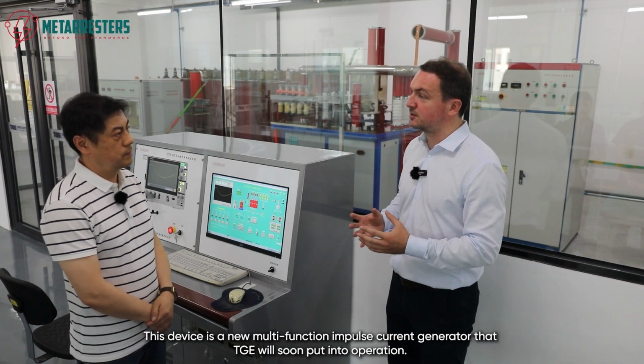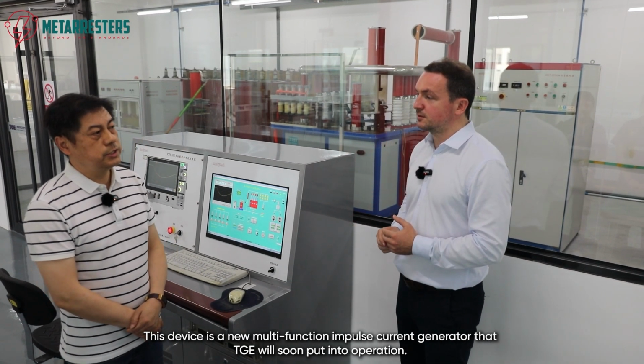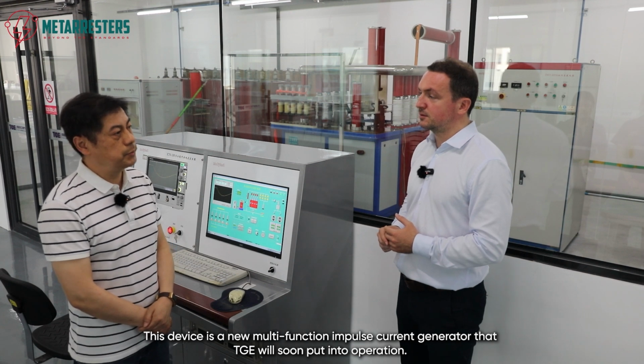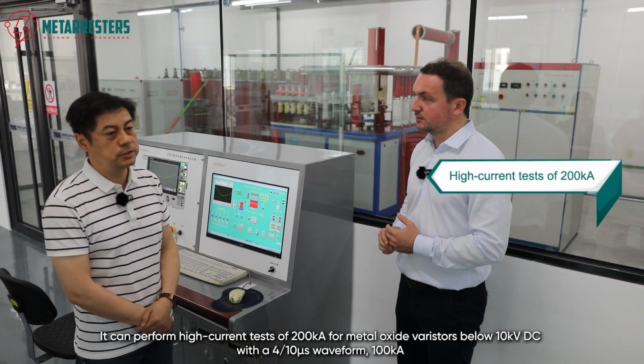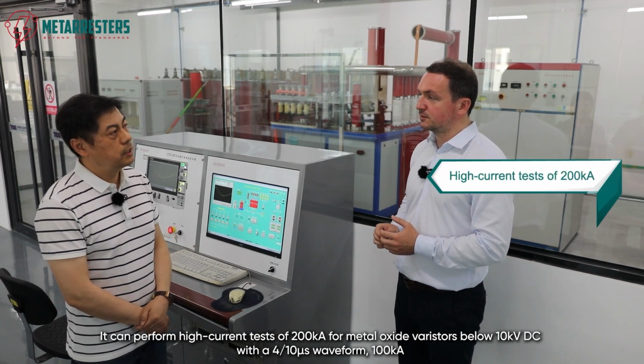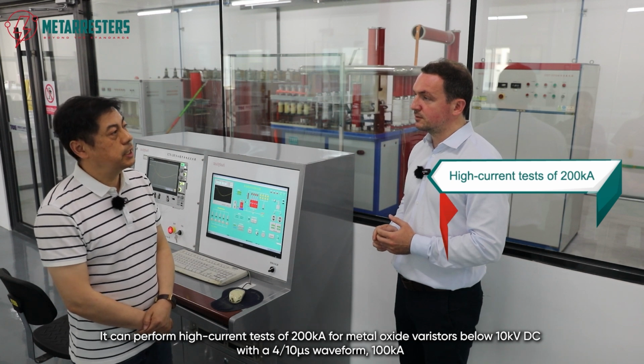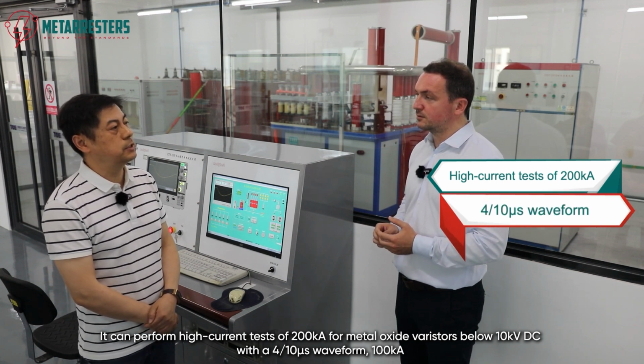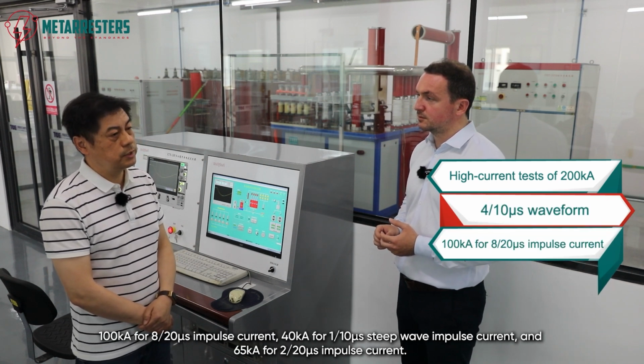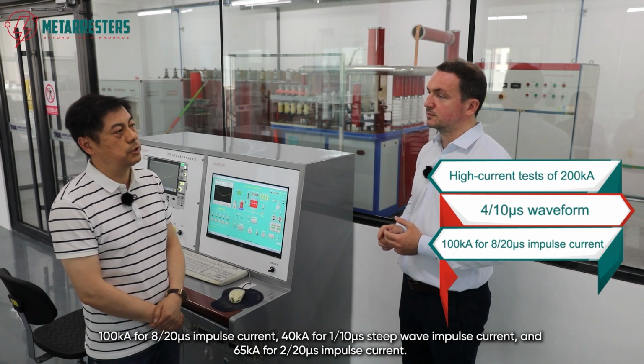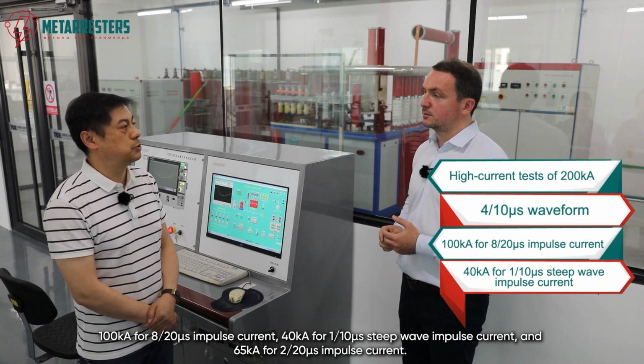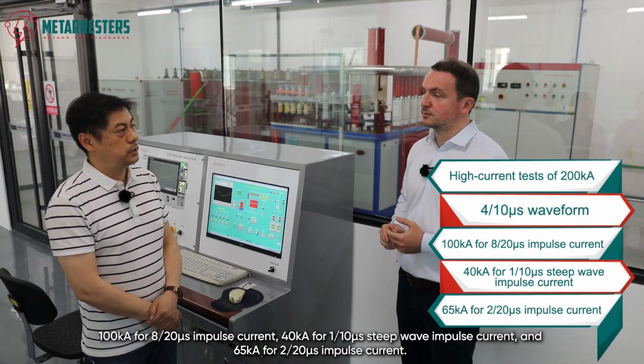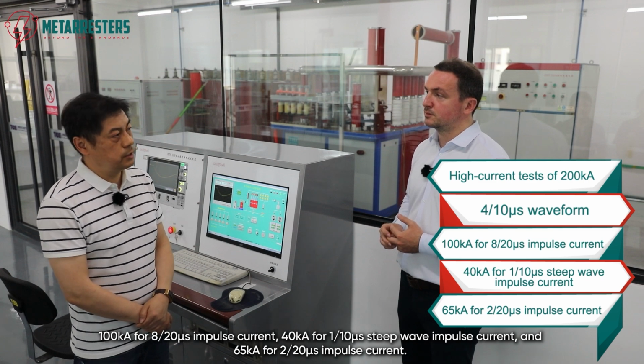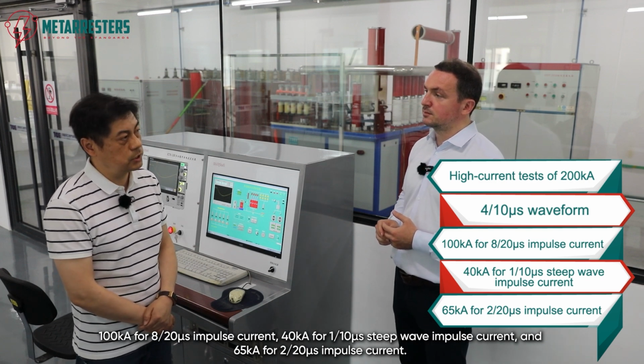This device is a new multifunction impulse current generator that TGE will soon put into operation. It can perform high current tests of 200 kiloamperes for Metal Oxide Varistors below 10 kilovolts DC with a 4/10 microsecond waveform, 100 kiloamperes for 8/20 microseconds impulse current, 40 kiloamperes for 1/10 microseconds steep wave impulse current, 65 kiloamperes for 2/20 microseconds impulse current.